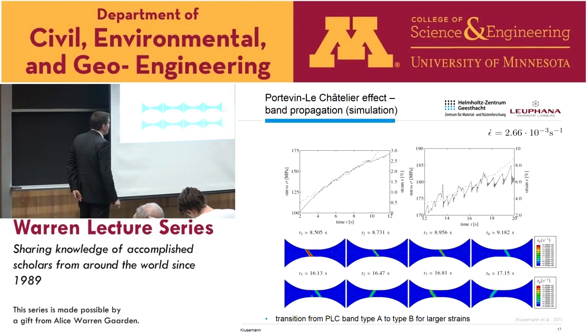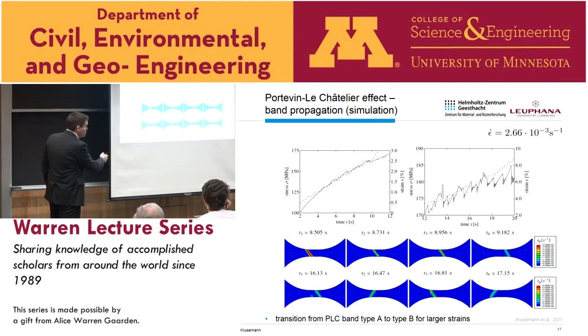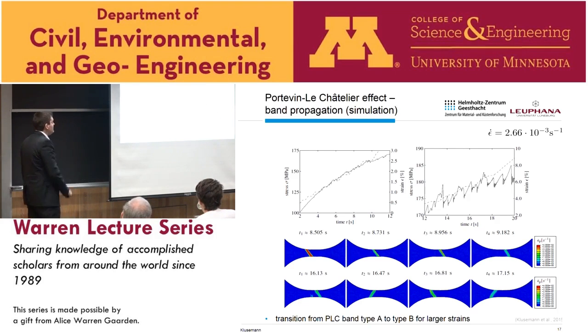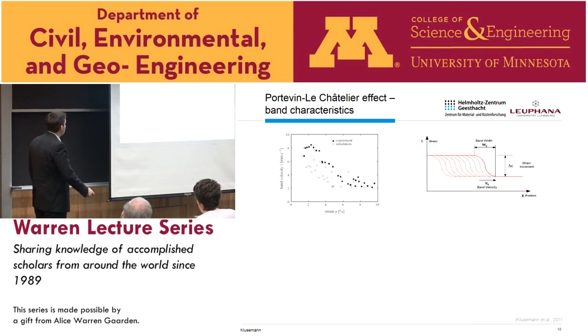And the same we investigated with the simulation. Here on the top layer you see a classical type A band, a band which starts and then continuously propagates through the sample, whereas here later on we have a PLC band which starts changing during the run through the gauge region. We even have a changed orientation, which we also saw experimentally, so our model was also able to predict, at least in tendency, the transition from type A to type B for larger strains correctly.